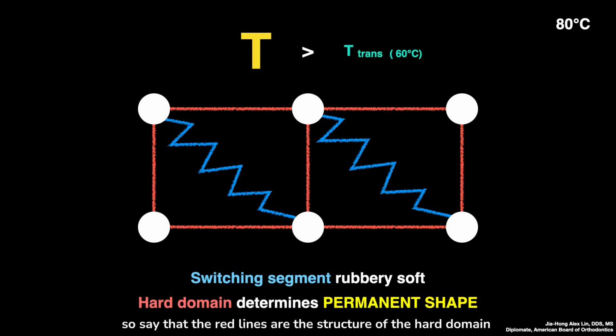So say that the red lines are the structure of the hard domain and the blue zigzag are the switching domain. Now the red lines, or the hard domains, have a higher TG, and the blue zigzag, the switching segment, has a TG of about 60 degrees, for example. So now if we put it in an 80 degree environment, because the temperature is higher than the TG of the switching segment, which is 60 degrees, the switching segments, or the blue zigzag, is soft, and it's the red lines, the hard domain, that is holding the shape of the aligner.